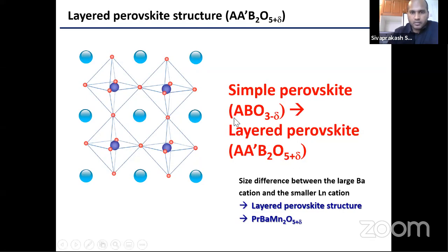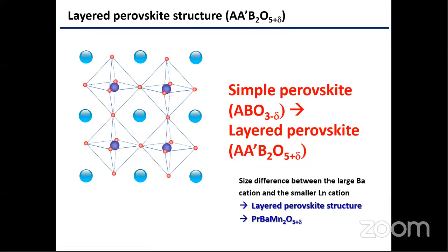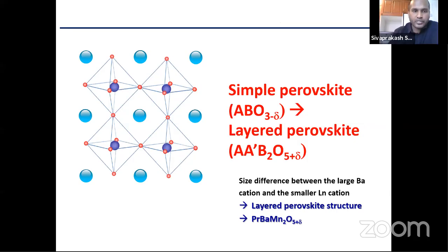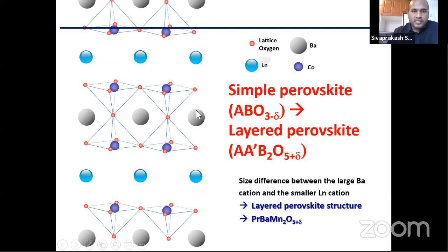For example, in the lanthanum site, we start doping a larger radius barium. In the A site, it changes its structure from a simple perovskite to a layered perovskite structure. Here you can see the barium, the lanthanum series, and the transition metal. Because of this, the layered structures are formed. In one layer only barium is present, then lanthanum is present, barium again, lanthanum again. Because of this reason, we call this a layered perovskite material. This formed because of the size difference between the barium and lanthanum cations.